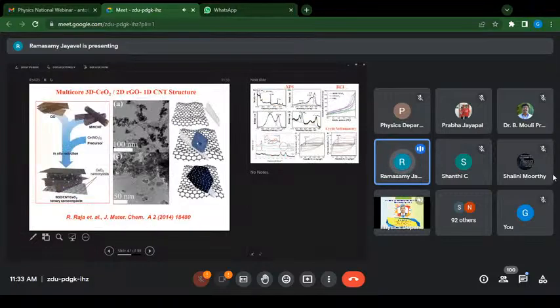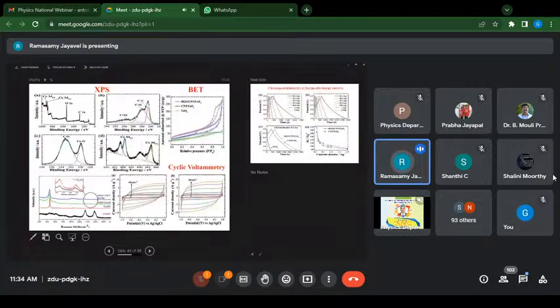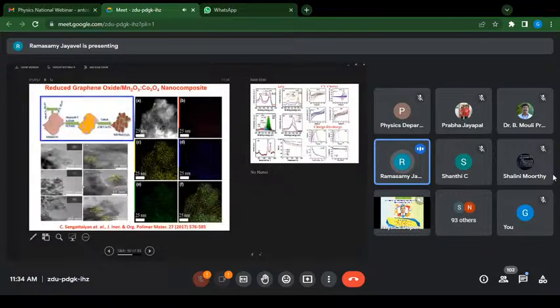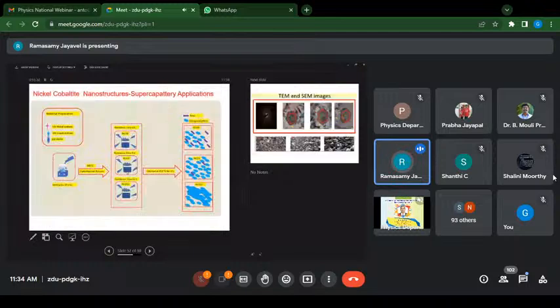And we tried to make three different combinations, taking a two-dimensional layer integrated with one-dimensional carbon nanotubes and mixed with three-dimensional cerium oxide nanoparticles. This was done by an in situ reduction process, which is also highly advantageous in terms of achieving higher stability with very high power density and energy density. We have tried different kinds of compositions, such as manganese oxide and cobalt oxide mixed with RGO. The important thing is that different kinds of morphology are possible with cobalt oxide and Mn3O4, and so they will have very high compatibility with the 2D layered materials, so that we can make very strong electrodes.